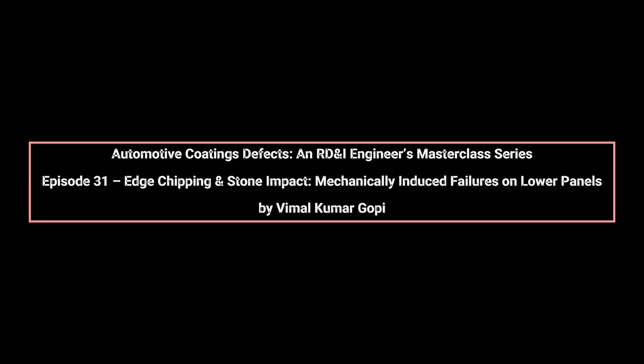From a troubleshooting perspective, OEM engineers focus on 4 key variables: film build and uniformity, crosslink density and cure, additive strategy, and panel support. Solutions may involve optimizing spray parameters, adjusting primer and base coat thickness, modifying bake profiles, or selecting elastomeric modifiers to improve energy absorption. Process controls are essential to ensure repeatable protection across all vehicles in the production line.